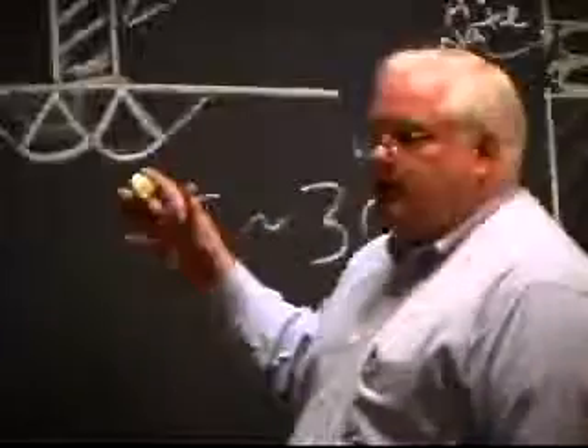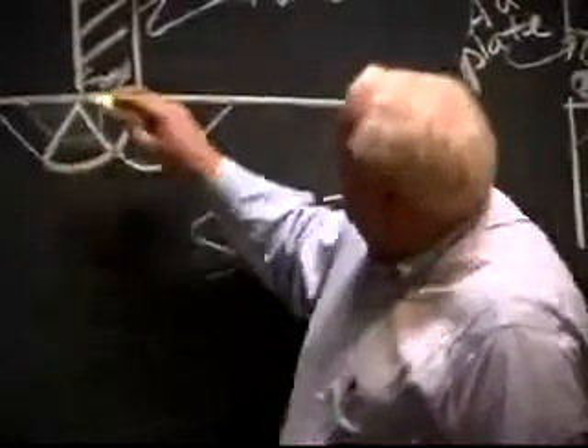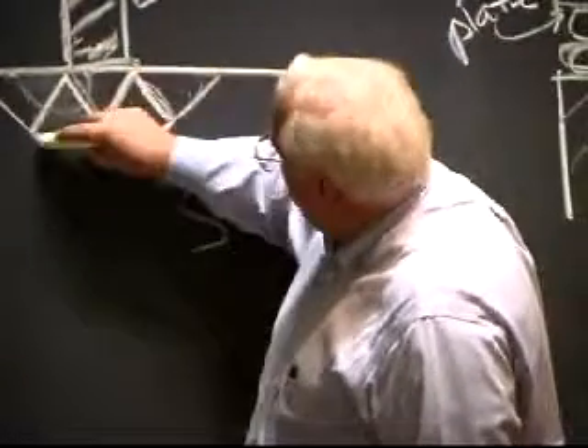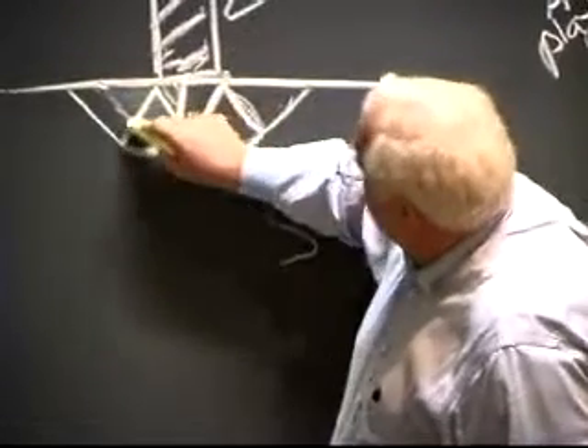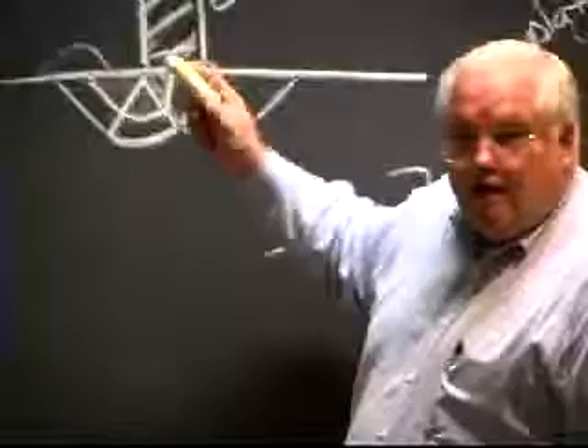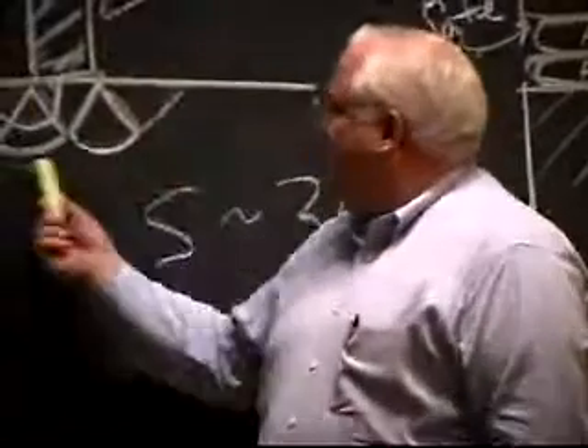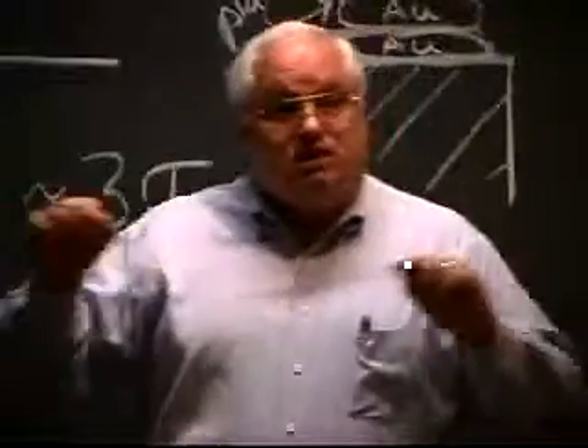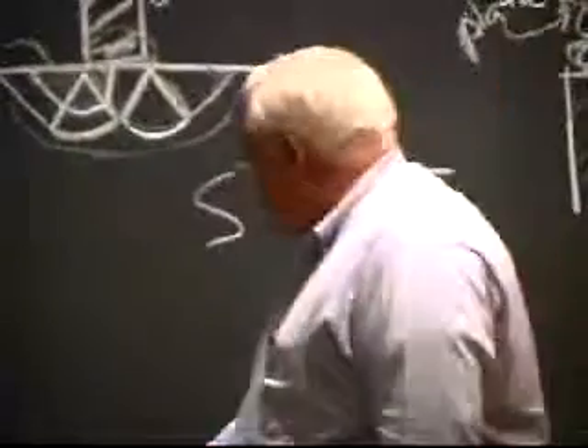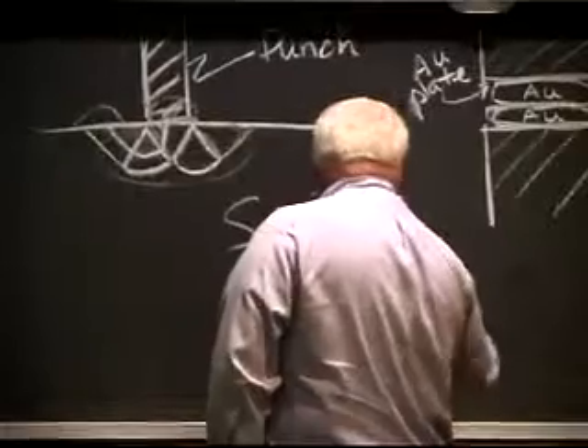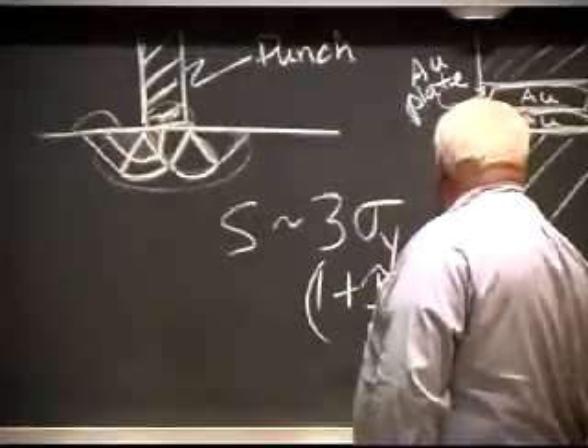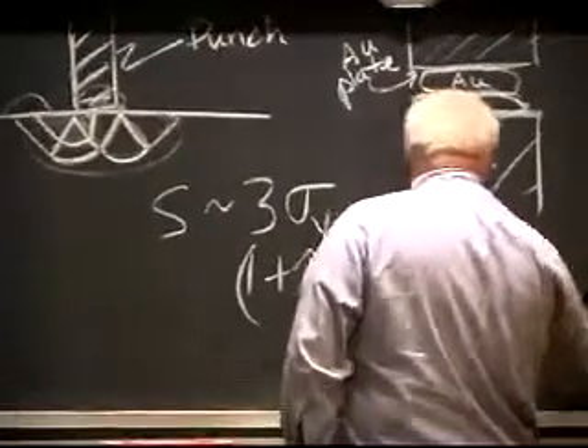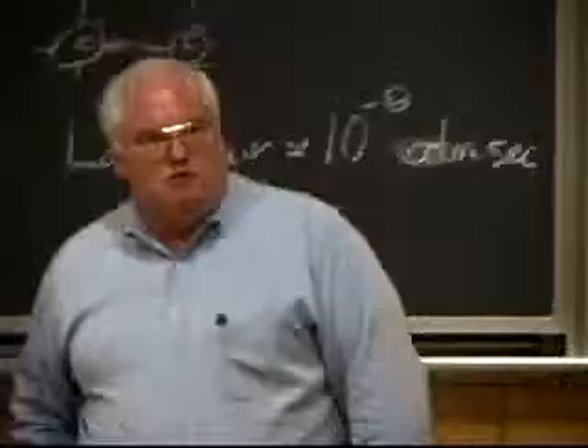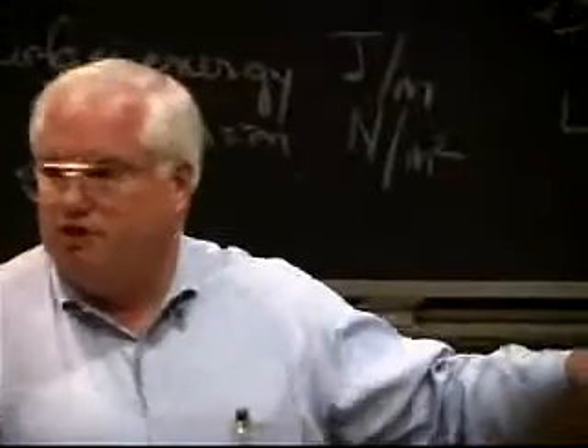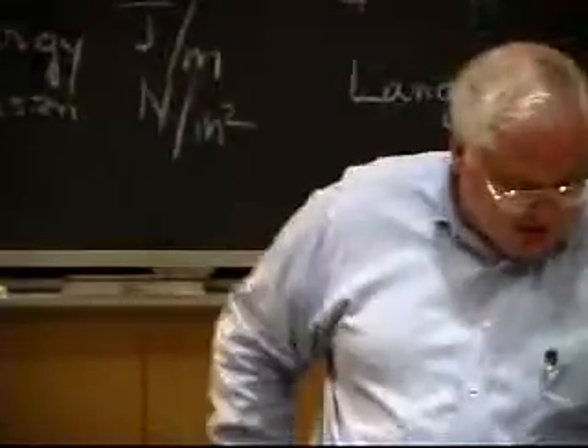Does that make sense? I've drawn this, for any of you that are mechanical engineers, as what's called a slipline flow field. A slipline flow field has these three triangles and these arcs, and it shows that the flow of the metal through here would be something like that. And you'd end up bulging the material out on the sides, right, if you push this in. Well, it turns out that volume is about 3 times that volume. The amount of force times distance, the work you do in this type of deformation, is about 3 times that. In fact, in slipline flow field theory, it's not 3 times, it's 1 plus pi over 2, times sigma yield, which is 2.57. Okay? But that assumes non-work hardened material. So if any of you are really interested in slipline flow field theory, it's the way you study deformation of materials.